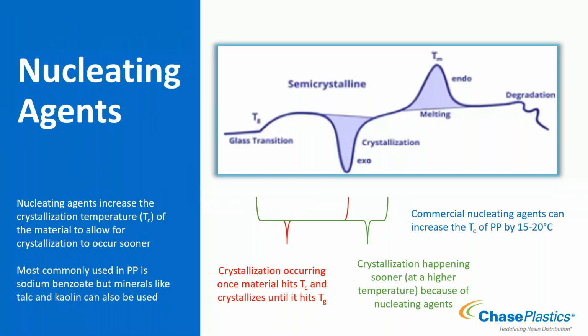What's happening is it comes down from its TM, or its melting temperature, which is when the crystals broke apart, you were able to flow it. Now we're cooling down, it hits what we call the TC, our crystallization temperature. Once it hits that, it starts to crystallize and form. And it continues to do so until you hit the glass transition temperature of the material. Your glass transition temperature refers to when the molecules can start to move. So as you might expect, if you go below its TG, molecules no longer have enough thermal energy to continue to move. So all the crystallization is happening between your TC and your TG.